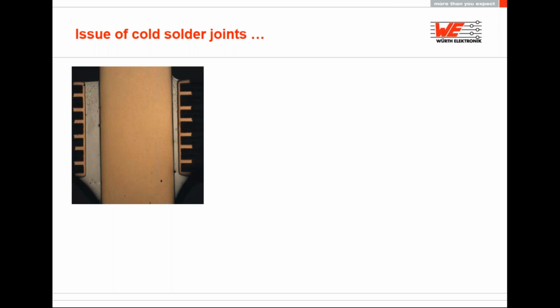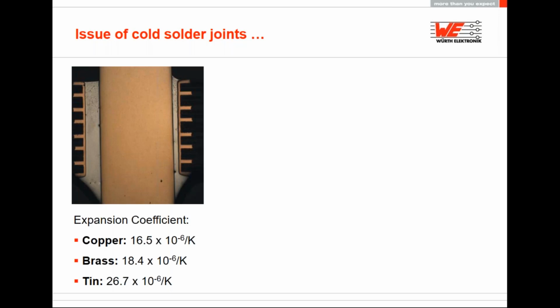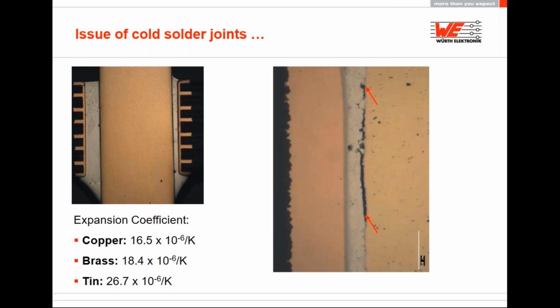So now there is an issue with cold solder joints, which I talked about in the beginning. When the process is done, there has to be a proper heat source so that the solder is made successfully. For THR, this is the case. We'll see about press fit in a second. With the image to the right, you can see a separation between the pin and the solder due to several factors, including thermal expansion, and the THR is a valid option, but making the process automatic has its limitations. As you can see in the image, there's a separation between the solder and the connector itself.